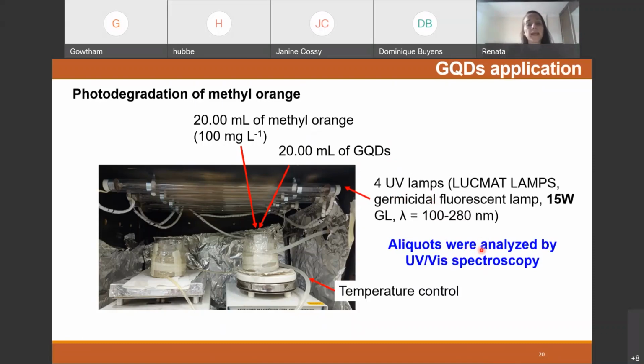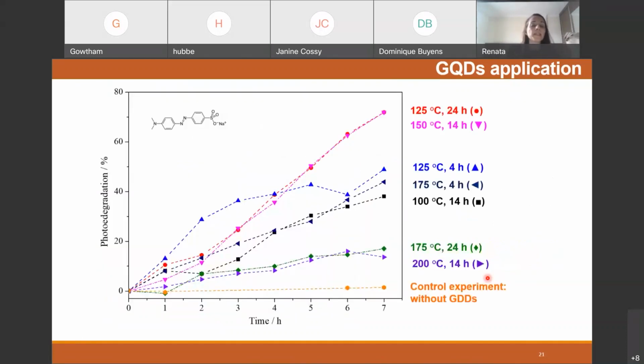Samples were analyzed by UV-Vis spectroscopy at different times of reaction. In this picture, it is possible to observe the results for each suspension obtained by the experimental design, and it can be observed that for the suspension obtained at high temperatures, the photodegradation was very low, below 20%.